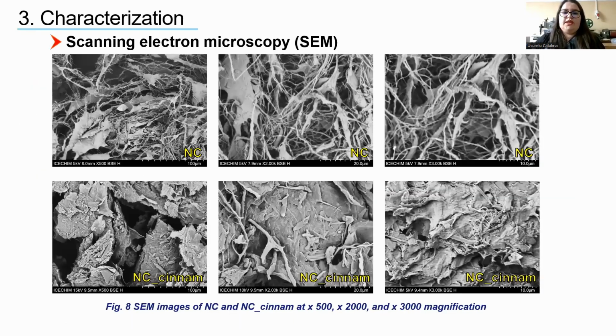The scanning electron microscopy images showed that after the chemical modification with cinnamaldehyde, the nanofibers were agglomerated. This may be due to the fact that the modification reaction with cinnamaldehyde took place in ethanol, which is a worse dispersing medium than water for cellulose, and could have led to the agglomeration of nanocellulose. But this agglomeration can also be due to the modification of nanocellulose with cinnamaldehyde, which led to an increase in their surface hydrophobicity and their agglomeration in water, because for the scanning electron microscopy analysis, the samples were cast on the carbon tape from water.